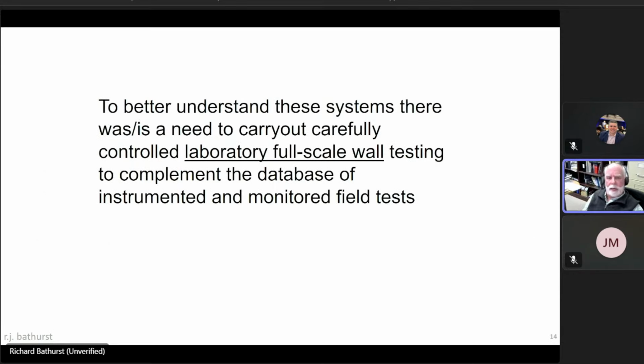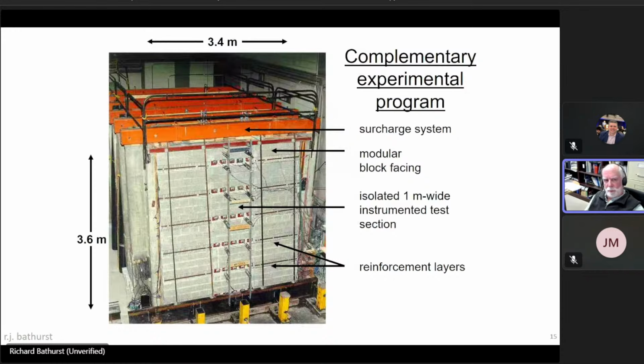So to better understand how these systems work, my colleagues and I decided what we need to do is carry out carefully controlled laboratory full-scale wall testing to complement the database of instrumented and monitored field tests. You know, it's very difficult to get a field test instrumented and monitored for obvious reasons. And there's also the issue of control of the construction and the instrumentation, etc., which comes up when you're trying to use a prototype field wall to make these measurements. So this was an incentive to develop an indoors laboratory testing program. And fortunately, at RMC, we had the so-called RMC retaining wall test facility.